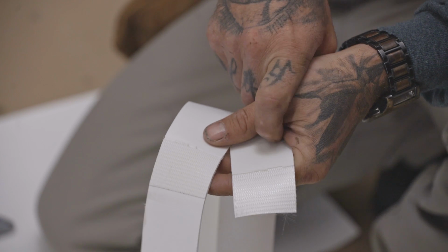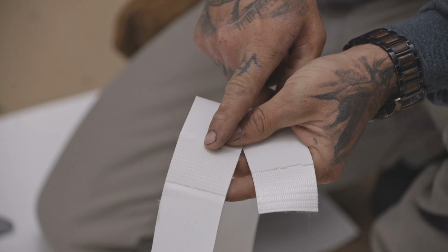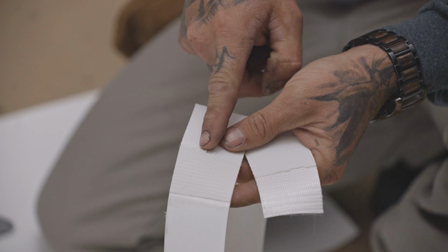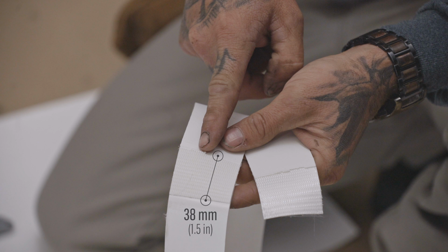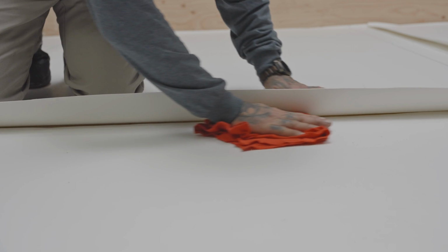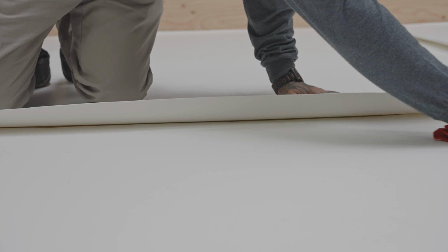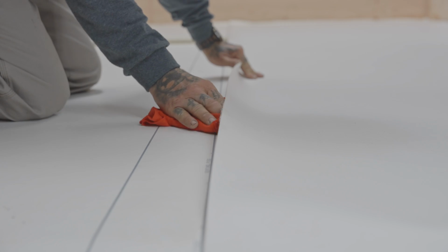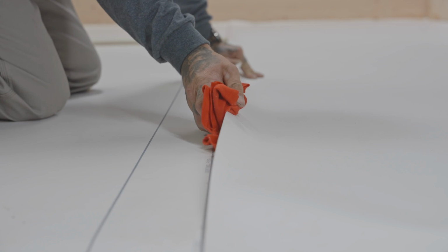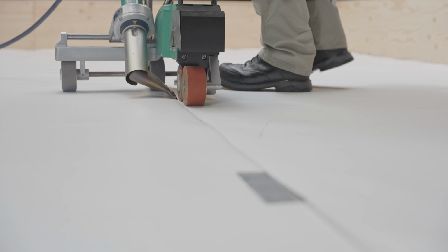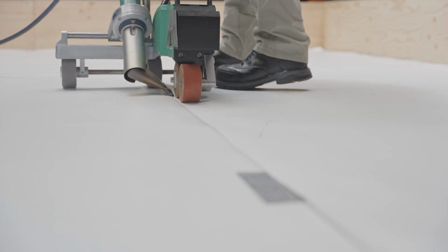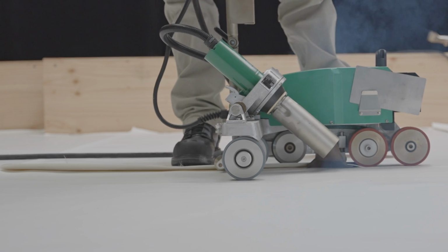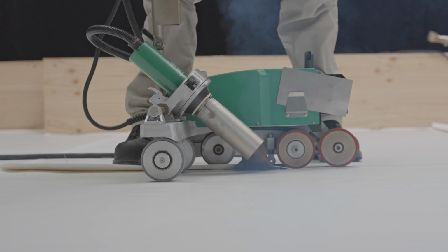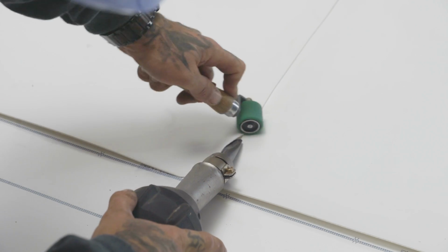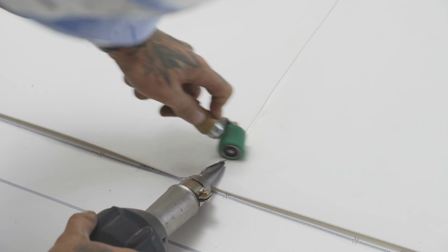A satisfactory weld is produced when the PVC does not delaminate from the reinforcing fabric and has a minimum width of 38 millimeters. Before welding the overlaps, make sure they are clean and uncontaminated. Clean them as needed with a non-greasy cleaner. You can now weld all overlaps using an electric hot air welding cart. Use the hot air welder for tighter spots and details.